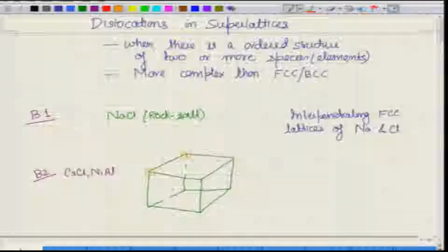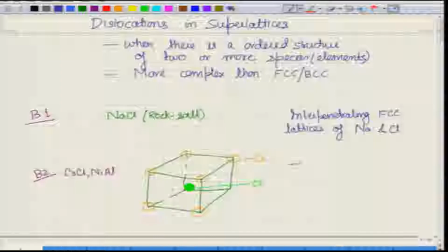So, one of the types of atoms can take these positions and another atom can take the body centered position. You can say this is chlorine and you can say this is cesium, but this is interchangeable, because if you connect all the chlorine atoms, it will itself form a simple cube, and at the body center of it will become the Cs. So, in this kind of structure these two positions are interchangeable, and therefore, in brief you can say this is two interpenetrating simple cubic structures.